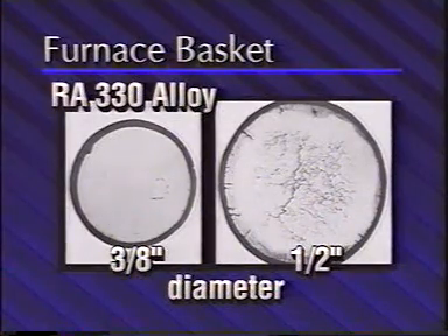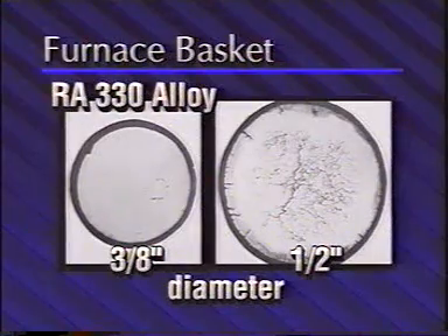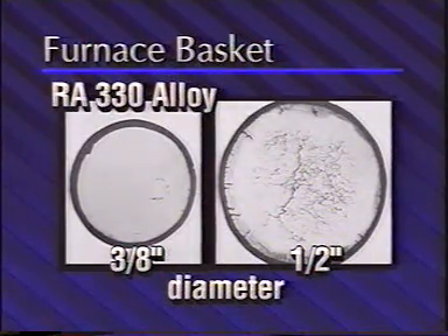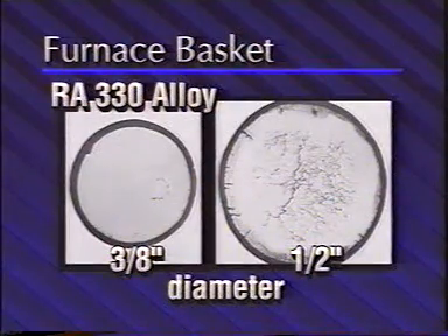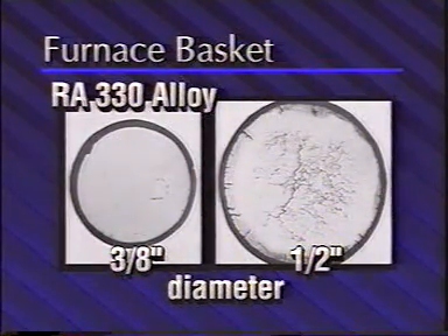Macrographs of RA 330 alloy bars taken from the same furnace basket show the effects of carburization. The smaller bar, 3/8 of an inch in diameter, shows no evidence of cracking. The half-inch bar exhibits severe cracking by thermal fatigue. Failure due to carburization generally occurs at room temperature, when the component embrittled by chromium carbide breaks as a result of impact or jarring. This type of fracture usually originates near the central portion of a fixture, basket, or tray.